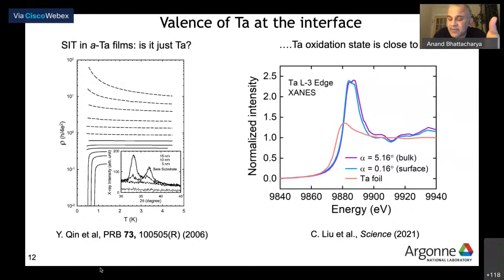So we went in with X-rays at the tantalum L3 edge. We did XANES at what we call a shallow angle and a high angle. The high angle is 5 degrees. The shallow angle is really glancing, at about 0.16 degrees. That's all done at the APS. And we looked for tantalum. At least as far as we could see, there was no elemental tantalum at the surface or the interface. What we saw was something very close to a tantalum 5+ oxidation state.